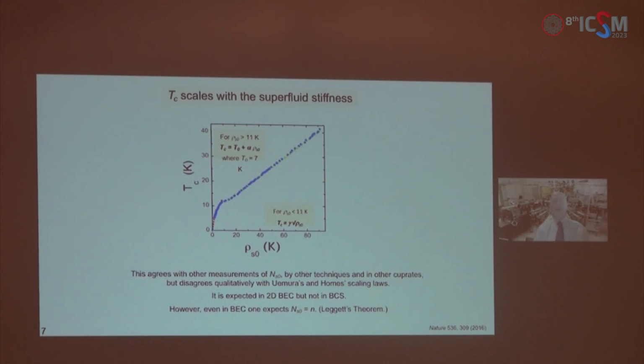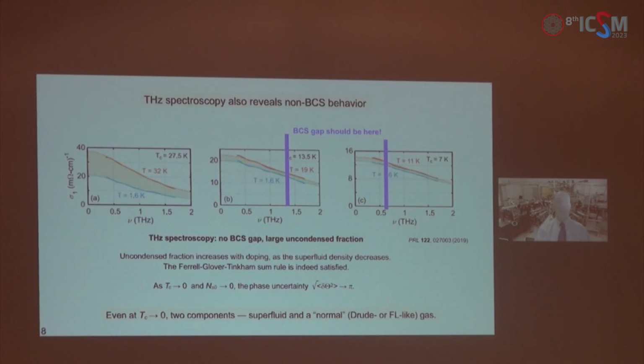Now, note, however, that there is a theorem that applies equally to both BCS and BEC, because in the two-fluid model, as temperature goes to 0, there are no excitations left, only the superfluid. So this is actually a very big problem to think about. And for us to be sure, we double-checked it and triple-checked it by several other techniques, one of which was microwave spectroscopy. And these experiments all showed the same thing.